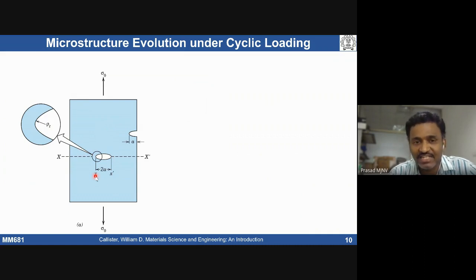What is the meaning of stress riser here, from a fracture mechanics approach? For example, on the surface you have seen this kind of intrusion, or sometimes we may see internal flaws because of some inclusion, and we may see crack formation. At the crack tip, in front of the crack tip, the stress is going to be less than sigma naught or greater than sigma naught? How much is it going to be? Any idea?